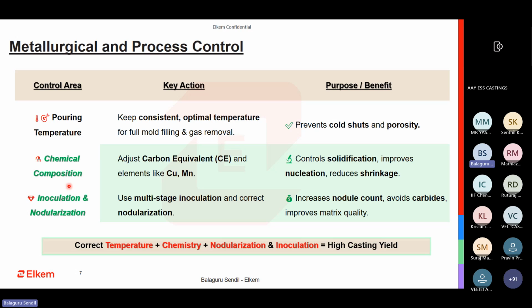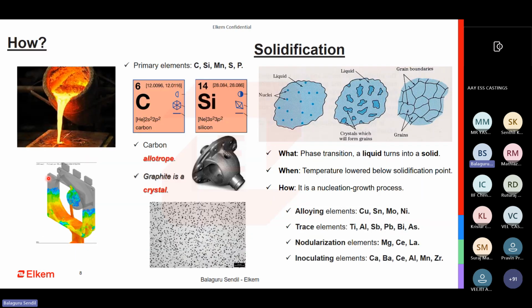So if you have the correct temperature, the correct chemistry, a very good nodularization process and minimum or good inoculation, then your casting yield can definitely be improved. Up to 5 to 7% yield improvement is possible. So that is huge savings for a casting, huge savings for a foundry. Even for a couple of castings that they make in large volumes, if they're able to take dedicated projects, then we will be more than happy to help along these lines where we feel we will be able to add more value to the customer. So before jumping into carbon equivalent, we have seen this slide.